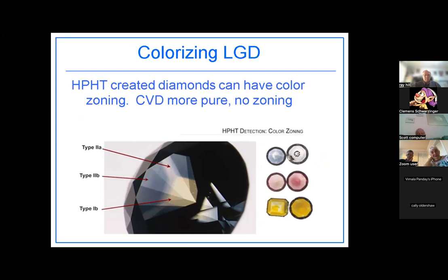Now your high pressure, high temperature created diamonds, a lot of times they end up with color zoning. And here you have a specific blue diamond, and you can see where one part of it's a type 2A, part of it's type 2B, part of it's 1B. With CVD, you have a little more control over the process, so you don't end up with the zoning. And you can imagine the difficulty with the HPHT trying to get a consistent color throughout the entire stone, because you're starting with basically an impure carbon form and hoping everything migrates in the right direction. And it may or may not pick up impurities along the way that will affect its eventual color.